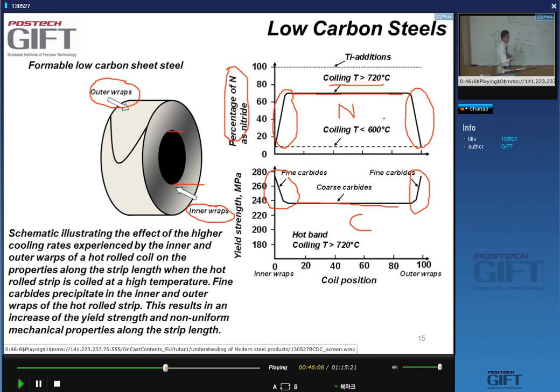And that was indeed the driving force in the development of IF steels: if we get rid of the nitrogen and the carbon, well, we can't get rid of it 100%, but we can stabilize them as carbides and nitrides, then our products will have much more homogeneous properties, because whether or not they have higher cooling rates at the start or the end will be irrelevant, yes? And that's indeed what you see. If you take the same steel and make titanium additions to it, titanium, as you know, is a very strong nitride former, yes? Titanium additions will lead to the full stabilization of the nitrogen, yes?